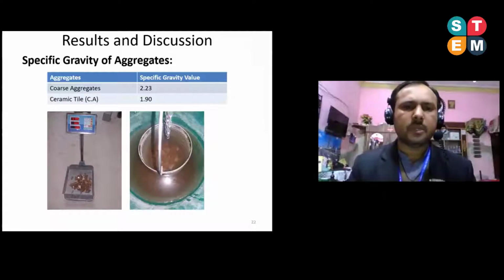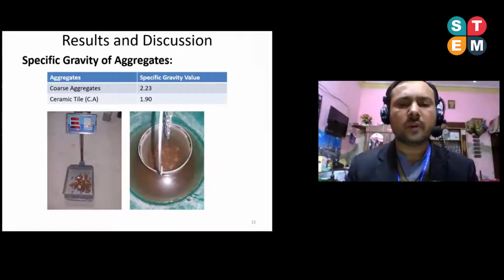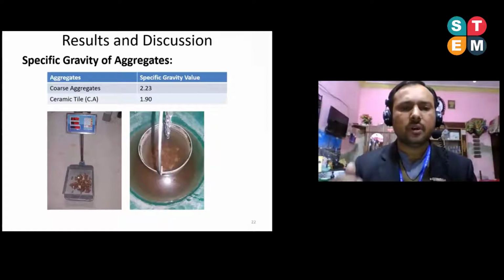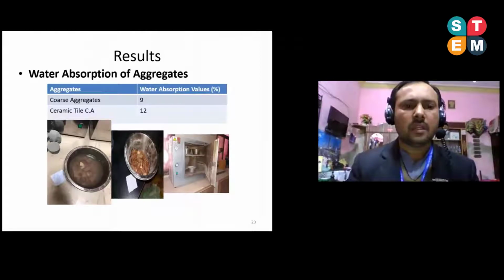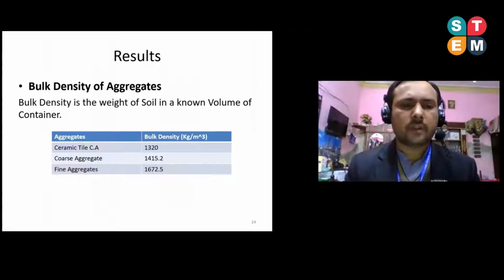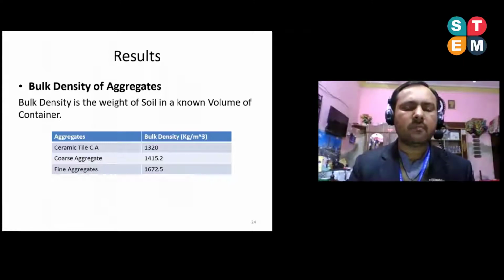These tests were conducted as a specific gravity test, and the specific gravity of coarse aggregate was found 2.23, and the specific gravity of ceramic tile was found in 1.90. So it shows that the specific gravity of ceramic tile coarse aggregate is lower than the actual coarse aggregate, and which reflect that we can also produce the lightweight concrete with the ceramic tile. This is some snapshots of water absorption test. So here you can see the results of coarse aggregate is 9 water absorption, but in ceramic tile, the water absorption is quite higher as compared to the natural aggregate, which is 12. These are results of bulk density of aggregates. Here you can see the ceramic tile coarse aggregate bulk density is 1320, and the actual natural coarse aggregate is 1415, and the fine aggregate 1672.